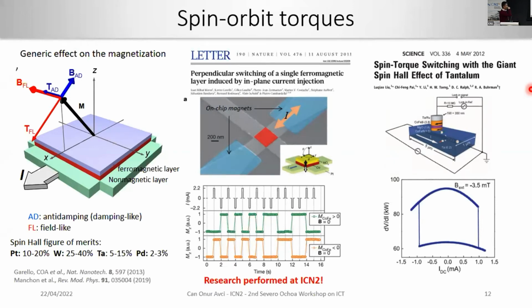Actually, this kind of magnetic manipulation by spin orbit torques had its first initial research performed here at ICN2 in 2011, in this paper here. My PhD supervisor back then, with his teammates, was able to control the magnetization of a single ferromagnetic layer by simply applying an in-plane charge current in this material, platinum, cobalt, aluminum oxide. This was followed up with other materials such as tantalum, where they were able not only to switch the magnetization, but also to build a magnetic tunnel junction and read the magnetic state by using the tunnel magnetoresistance.